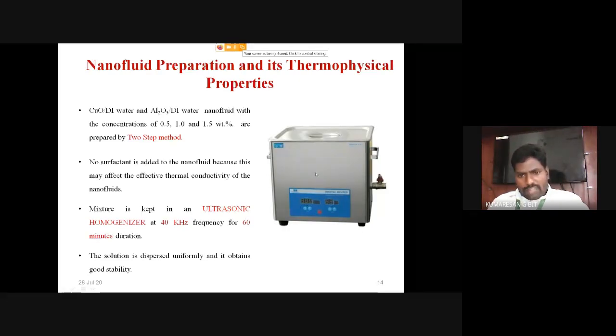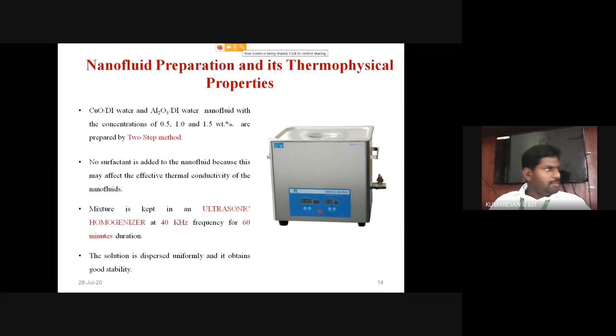Then these are the methods of nanofluid preparation used in the evaluation of the thermophysical properties of the nanofluid. First, this device is called an ultrasonicator. This ultrasonicator is used to improve the stability of the nanofluid. Okay. Here I have used copper oxide nanoparticles suspended in DI water, and additionally aluminum oxide nanoparticles also suspended in DI water. These two nanoparticles' performance is compared. Okay. Here both the nanoparticle concentrations are taken as 0.5, 1 and 1.5 weight fraction. These two fluids are prepared using the two-step method. In addition, no surfactants are added to the nanofluid, because the surfactant may affect the effective thermal conductivity of the working fluid. Then the prepared mixture is kept in an ultrasonicator with a frequency of 40 kHz for a duration of 60 minutes to attain good stability.